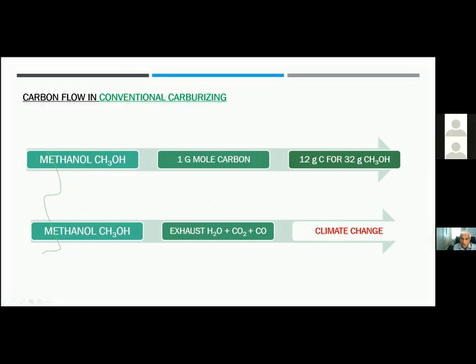If you look at conventional carburizing, let's take the example of methanol. You can use endogas, which is a mixture of things. Let's take methanol. Methanol is CH3OH. So again, you have 1 of carbon, 4 of hydrogen, and 1 of oxygen. So for 1 gram mole of carbon, which is 12 grams of carbon, you have 32 grams of methanol because oxygen is 16. So you realize that your inherent efficiency of carbon transferred from the medium to the component is 12 by 32, which is about 36, 37%, compared to 92%, which is the inherent quality of transfer of tomorrow's carburizing.